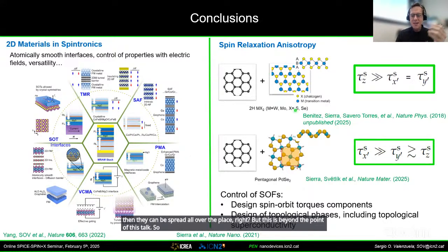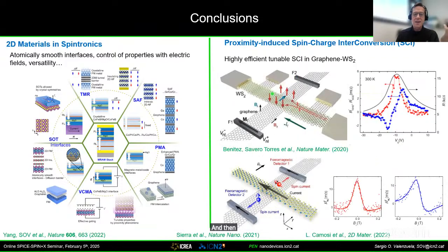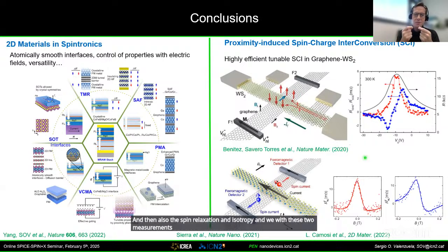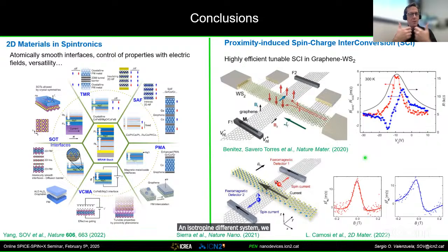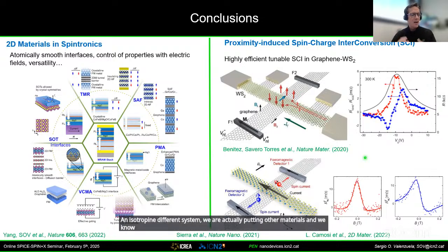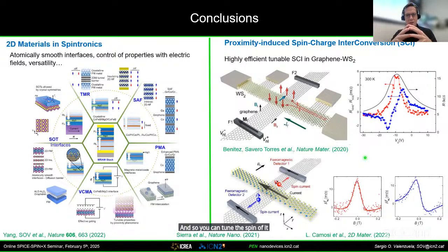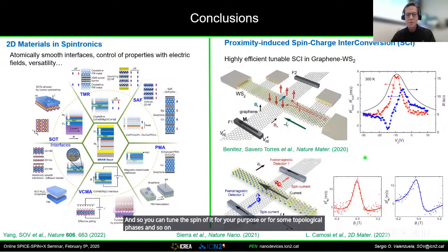So I showed you the spin relaxation and anisotropy, 2 cases in which you have this hierarchy of relaxations. And with these 2 measurements, we can get information on spin lifetimes, and we get information of the spin orbit coupling. And this allows you to start understanding how to get anisotropy in different systems. We are actually putting other materials, and we know a little bit what's going to happen. And so you can tune the spin orbit for your purpose, or for some topological phases and so on. So with this, I just want to conclude.